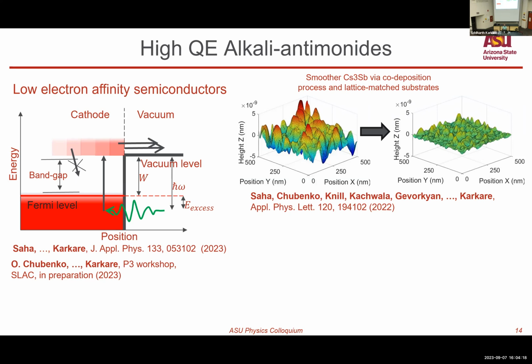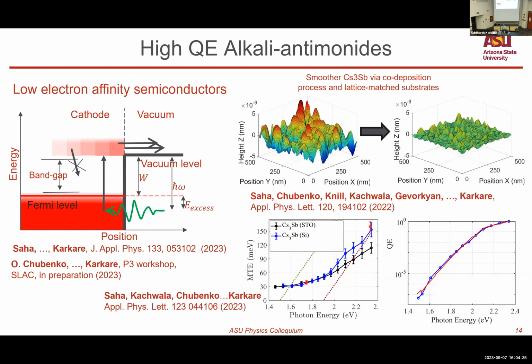And when we use lattice match substrates like strontium titanate for growing these films, that gives an even smoother surface, a nearly atomically flat surface that you can see here. We recently characterized the mean transverse energy and quantum efficiency from these materials to an unprecedented detail. And close to the threshold, we see near kT limited MTEs. The quantum efficiency at these is significantly higher than what we get in metals.